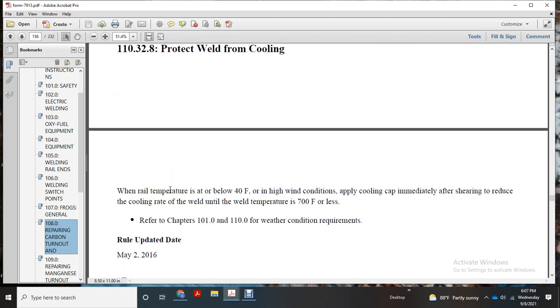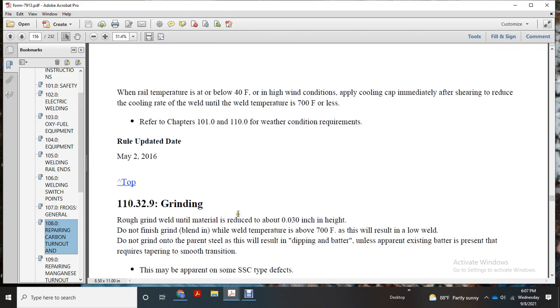Protect the weld from cooling. When rail temperature is below 40 degrees or in high wind conditions, apply the cooling cap immediately after shearing to reduce the cooling rate of the weld until the weld temperature is 700 degrees Fahrenheit or less. Refer to chapters 101 and 110 for the weather condition requirements.